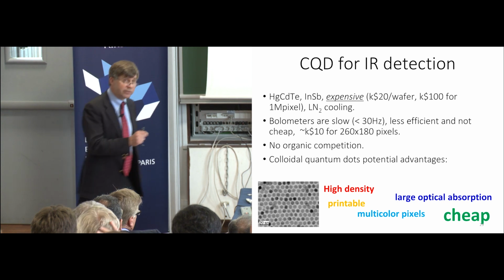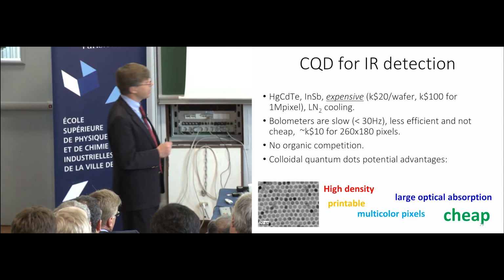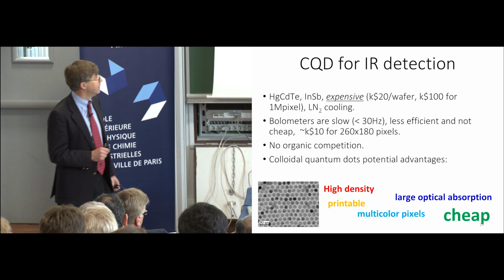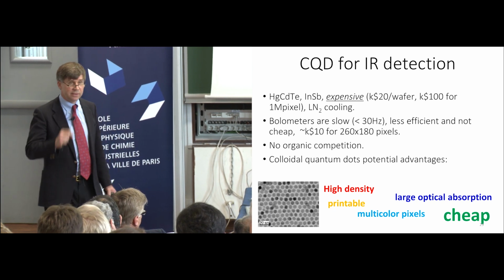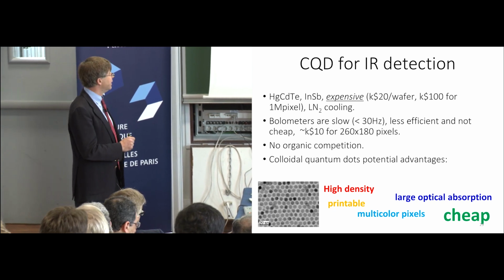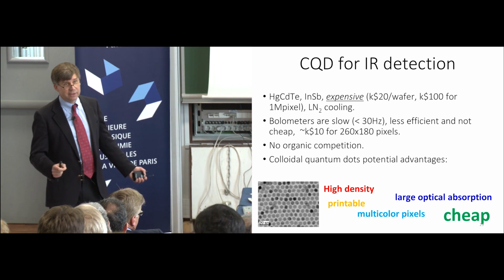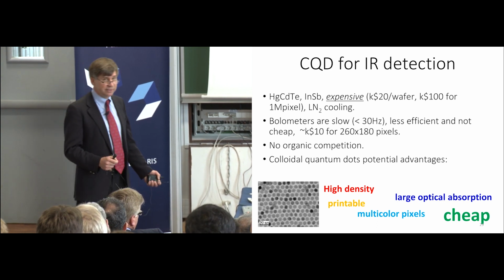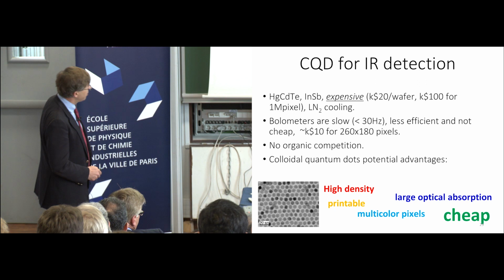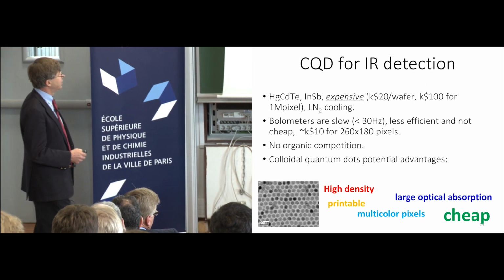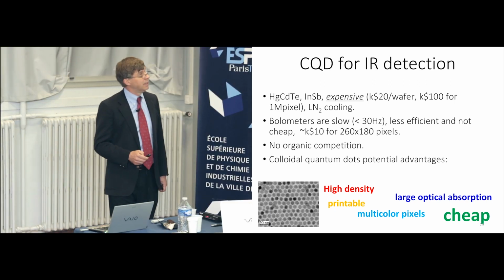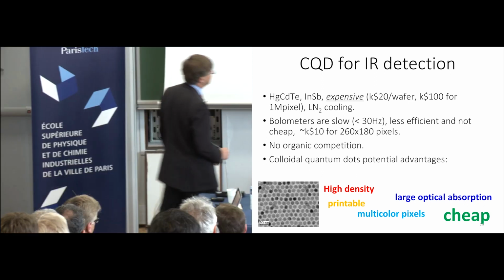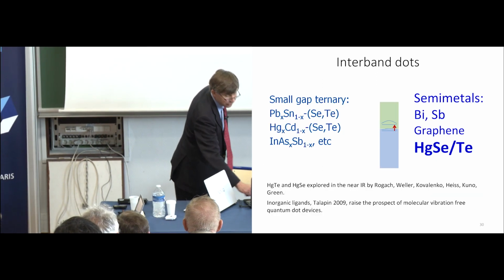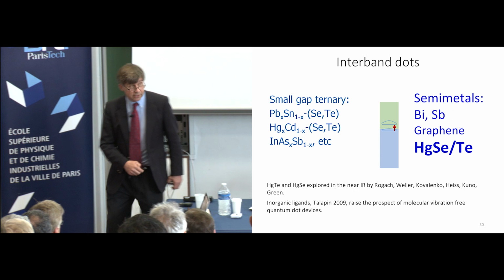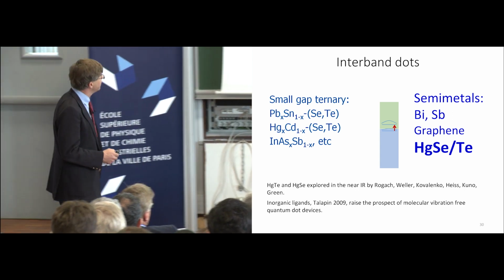Now, there is something special about quantum dots, which is that there is no organic competition with the infrared. You know, we always say we make this nice core shell dot, they fluoresce, but organic dyes fluoresce beautifully. Organic LEDs work beautifully. So quantum dots have to work hard to make it competitive. But in the infrared, at least there's no dyes, so that's good. So that's why I chose to work in this area, and also, I guess, because of my background in infrared spectroscopy.